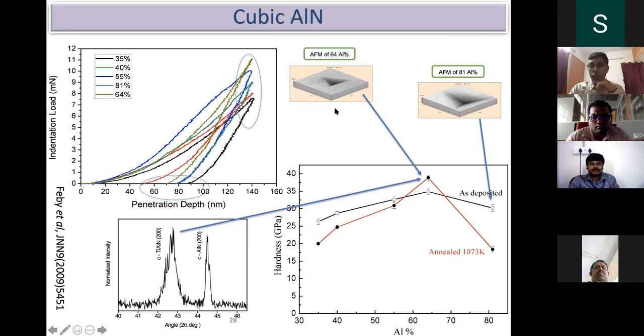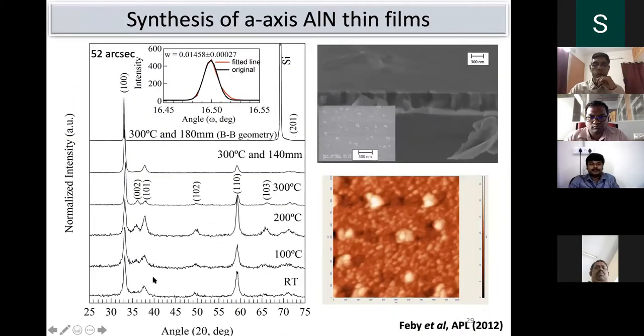And 64% aluminum nitride, the nano indentation profile looks almost a sinking type. But when you see this for an 81% aluminum doped system, it's a kind of sinking as well as the pile up both exist. So that means the annealing in the 64% aluminum doped system, you can get aluminum nitride in the cubic form, and the width is also very large. That means this is nanometric size. Probably it would be less than 6 or 7 nanometers. From this we can understand cubic aluminum nitride exists. Well, this is the highlight of our talk today.